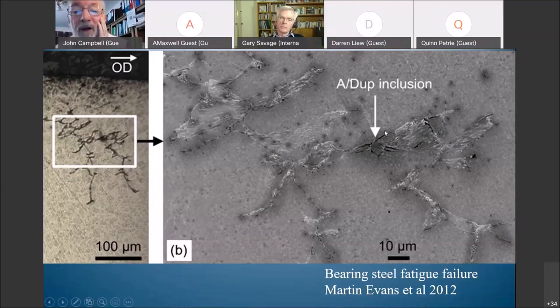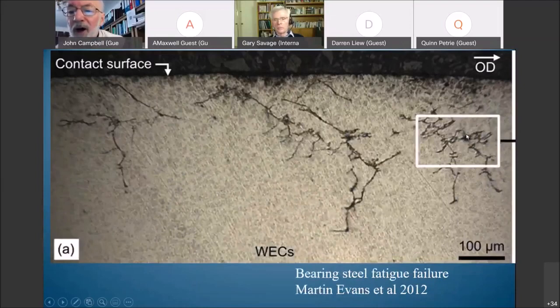And so what's happening, if we go back, here is a tiny, tiny fatigue event taking place, where the fatigue crack is moving out step by step, making beach marks to give its progress, cycle by cycle, extending. So there's an extending crack in here that's fatiguing away. And probably at other places throughout this network of WECs, there are little fatigue events going on which are linking